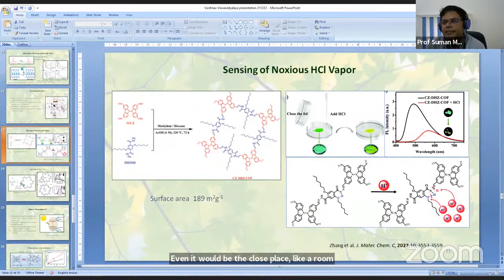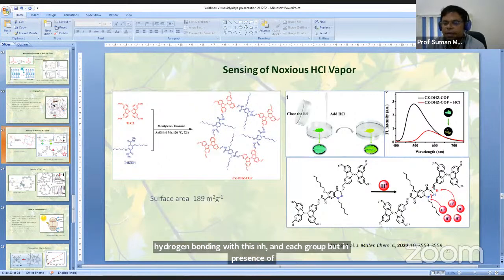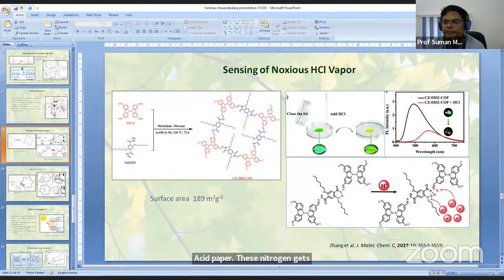And it has been sensed because when the acid vapor is not there, it forms this kind of structure which is hydrogen bonded, where this ether linkage makes some hydrogen bonding with this amide NH group. But in presence of acid vapor, this nitrogen gets protonated and this linkage gets clipped. And therefore the bleaching of the COF.